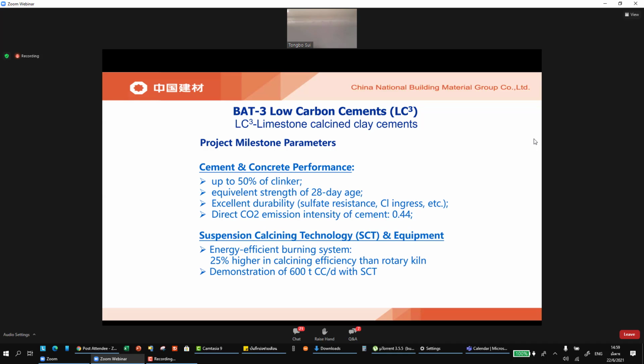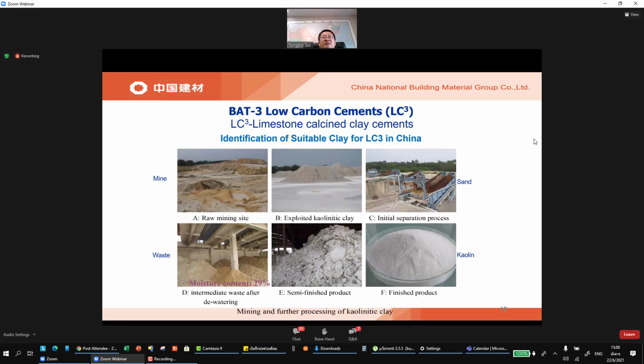This is a kind of flash calcining system. We expect to use such a system to produce the calcined clay more energy efficiently. We also demonstrated the project outcome by trial production of calcined clay at 600 tons per day in the system. The raw material we identified in China is an intermediate waste from the beneficiation process of kaolinite in southern China, where a lot of such silicate soft clay, kaolinite clay, can be found.